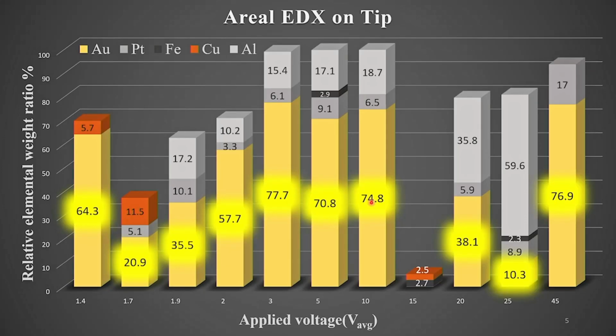Now let us move to the more exciting results on the tip. You can clearly see here we have a huge amount of gold on the tip, almost at all voltages. Also, some platinum has appeared, but here the EDX machine resolution is limited, so the machine is not able to distinguish between gold and platinum EDX peaks. So here you can see the weight percent of gold at different voltages, which is quite significant.